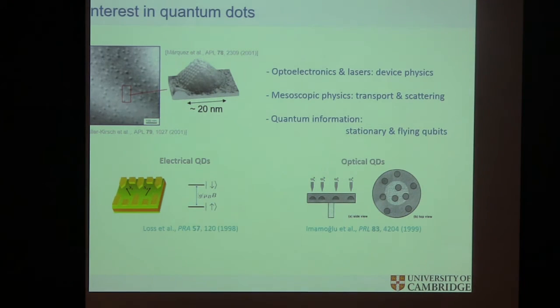semiconductor. But if you pay attention in the very beginning stages, between one monolayer of indium arsenide, which is forced to have the same lattice constant as the gallium arsenide below, because it's so much more dominant, versus two, where it would start kicking in, or bringing in its own lattice constant, there's a mini phase transition. It's actually 1.6 monolayers. That very thin, stretched layer becomes little bubbles, droplets, all of a sudden.